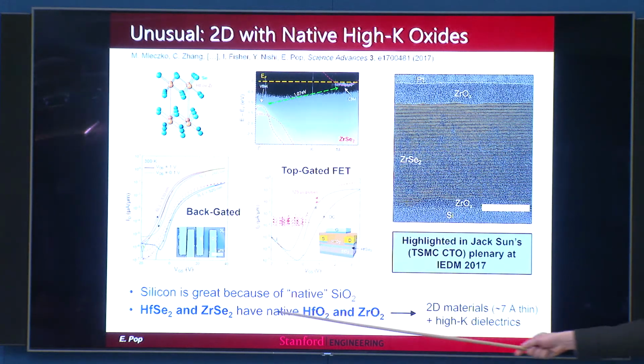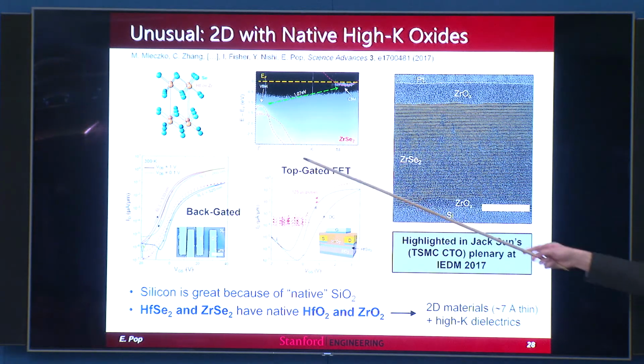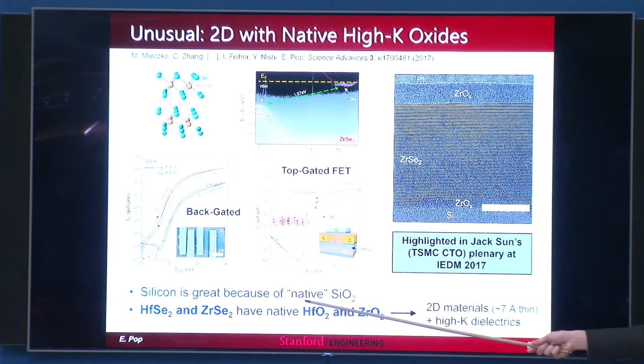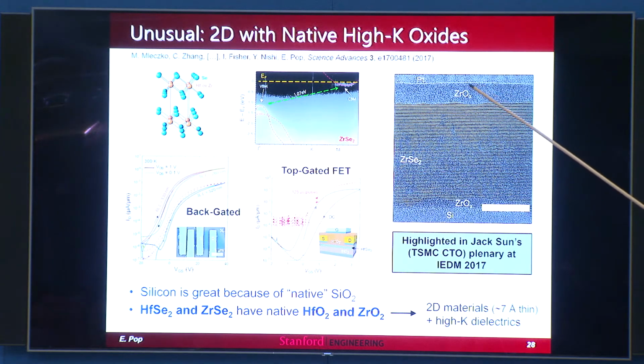These are different selenides. These are hafnium selenide or zirconium selenide. Note for now, these are multi-layers. Everything else I've shown you pretty much is monolayer, but these are multi-layers. And the way we started working with these selenides is actually kind of a reverse engineering thing, because my student Michael Mletzko started thinking about, hey, if silicon is great because it has native SiO2, what material will give us native hafnium oxide or zirconium oxide? And it turns out the answer is hafnium selenide and zirconium selenide are such materials. They happen to be 2D materials. And so here you see a TEM of zirconium oxide formed natively on zirconium selenide.